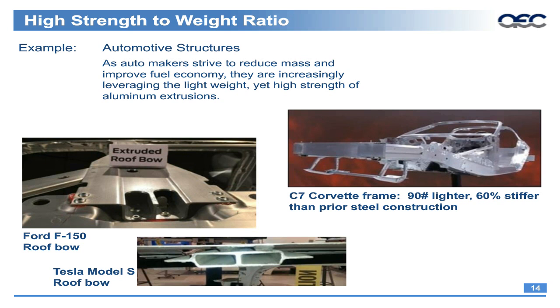So as we start to talk about more efficient vehicles, we need to be able to create stiffer and, most importantly, safer structures for use in the automotive industry. But a key in this is not only the material, the aluminum material, but then also the profile design. As you can see in a lot of these profiles, specifically in the Tesla Model S roof bow, which is the profile on the bottom, the wall thickness of the part is not uniform around the entire profile. And with an aluminum extrusion, you can actually move the metal and only put material where the material is needed. So therefore, you're not only creating a stronger structure in being able to customize where that material goes, but also a more cost-effective structure because you're not putting more material in there than what is needed.